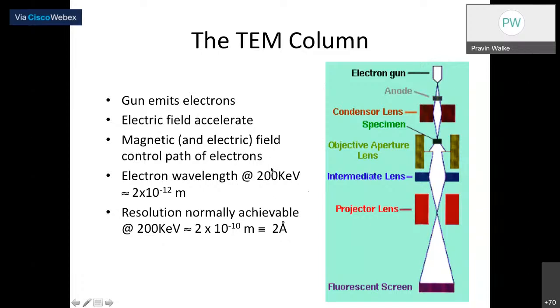But here, in order to work the TEM, the electron wavelength is 2 times 10 raised to minus 12 meter if we use 200 keV, and electrons can operate from 100 keV to 400 keV. So there are variant versions of the transmission electron microscopes available. If you go to a higher potential difference, let's say from 200 to 300 to 400 keV, you will find that the wavelength of the electron goes down and down, right? And then you can improve the resolution. So, for example, with 200 keV electrons, the resolution limit is up to 2 angstrom. So someone can go up to the 2 angstrom limit when they use this kind of TEM with 200 keV, because of this potential difference V, remember the first formula, lambda depends on V, right? So this V is this one, and that wavelength lambda has been tuned, so that has to help.